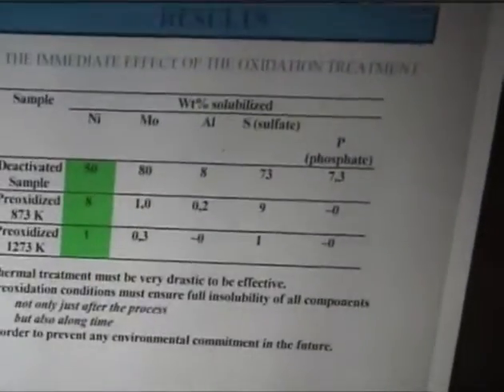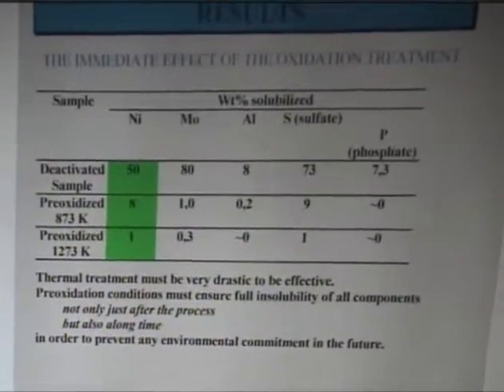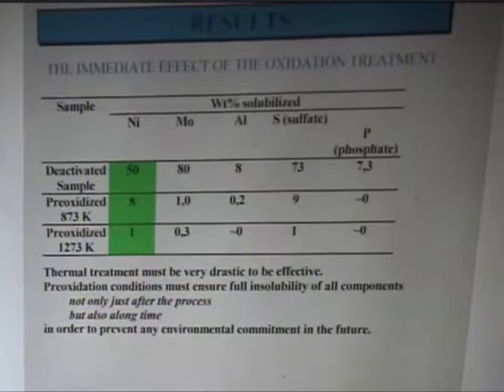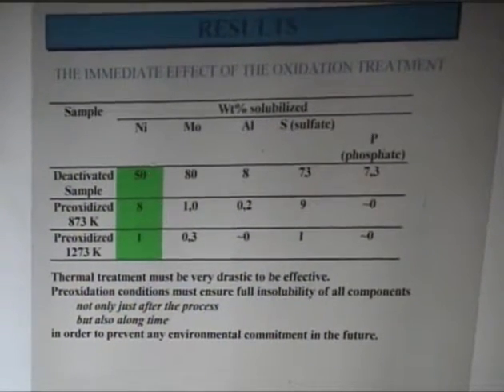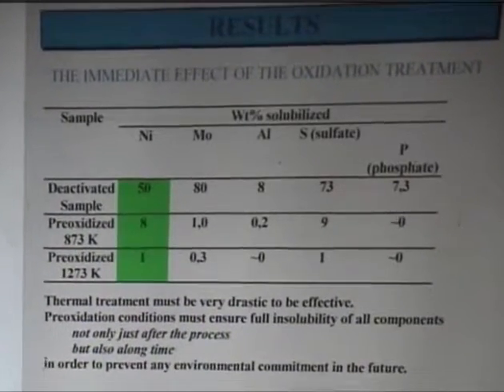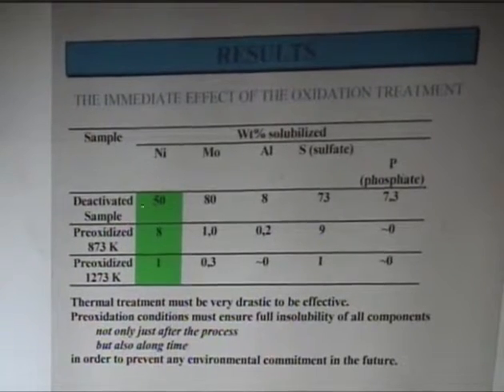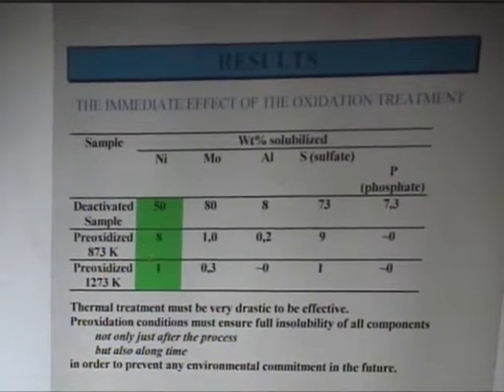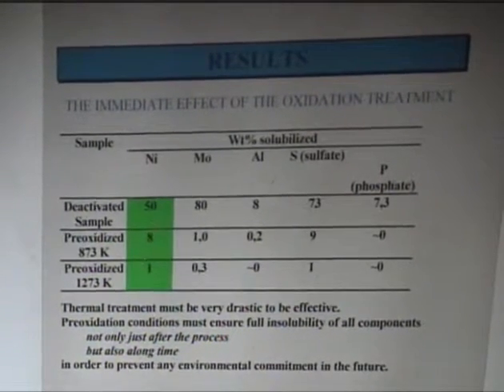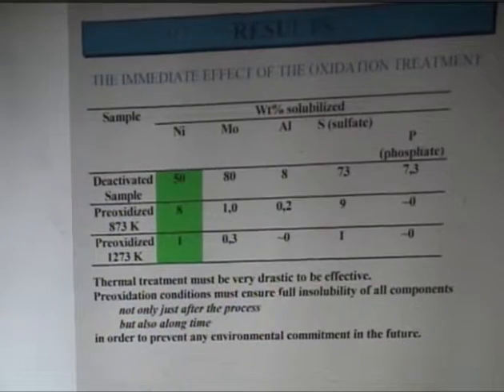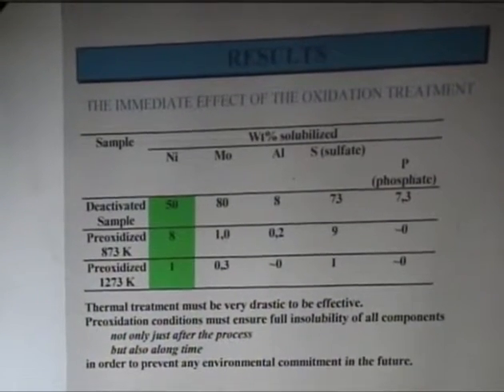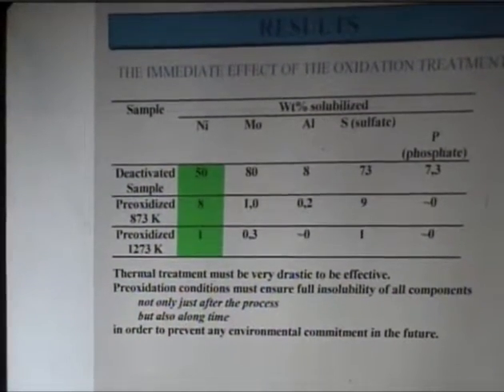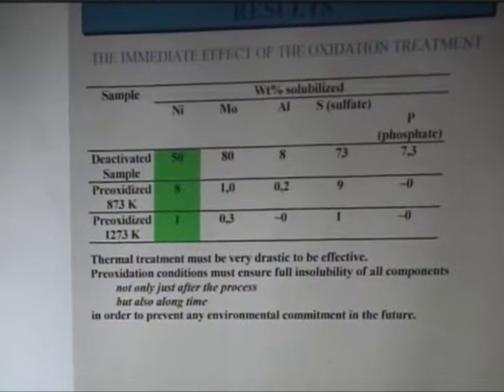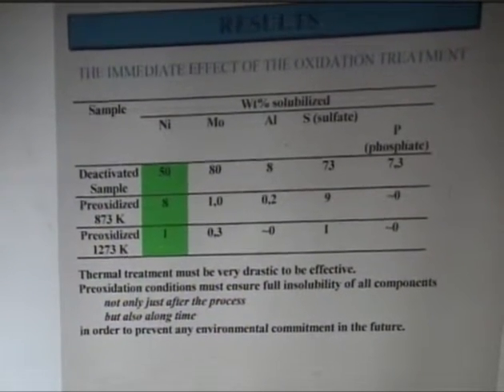Another set of results concerns the immediate effect of the oxidation treatment on the solubility of the sample. For the deactivated sample, more or less half of the nickel was soluble in water or in methanol after treatment. For the preoxidized samples, the solubility level decreased 50-fold in the case of the sample preoxidized at very high temperature. In fact, again, the thermal treatment must be very drastic to be effective. Preoxidation conditions must ensure full insolubility of all components, not only just after the process as seen here, but also along the time as seen in our previous results, just because we must prevent an environmental commitment in the future.